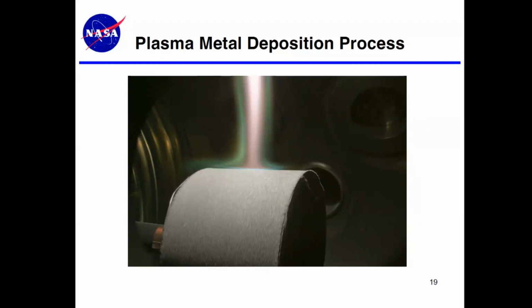Now the parameters for the deposition process can be controlled. If you use a very small particle size metal and use, let's say, a hot plasma, you can fully melt the metallic particles, and they'll form essentially a densified layer on the fabric. If you use larger particles or a less energetic plasma, you can just melt the outsides of the particles, and you can get essentially a porous material formed on the fabric. Show the next chart, please.